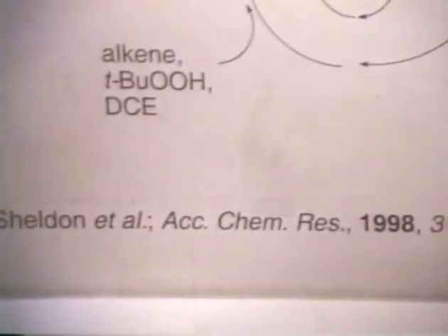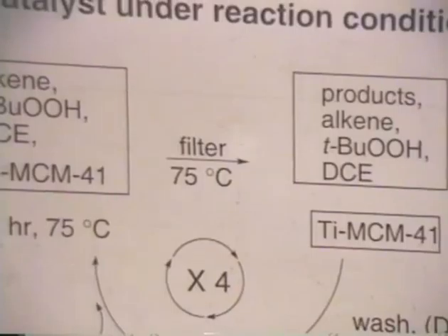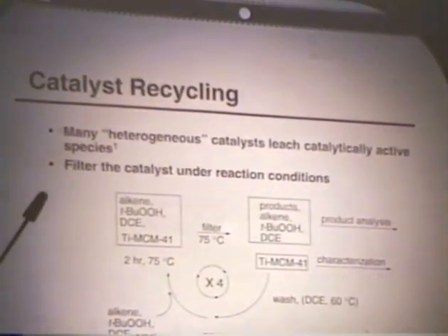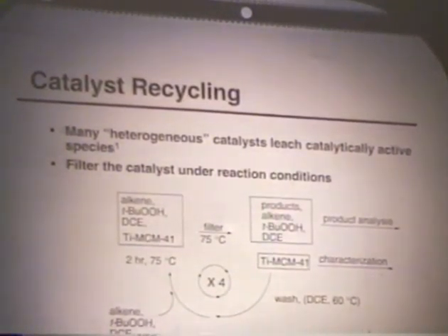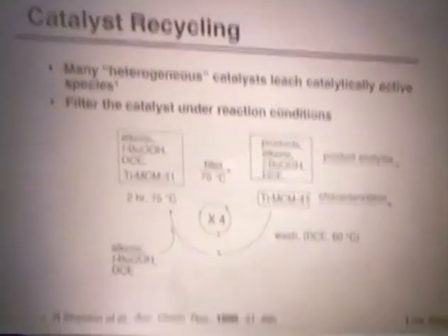Now, one of the interesting things comes as you recycle these materials. In any of these oxidation catalysts where one is doing liquid phase oxidations, one always needs to look for leaching of the material from the surface, and which potentially generates activity in the solution. And one then needs to be able to figure out what's heterogeneous catalysis and what's homogeneous catalysis in these cases.